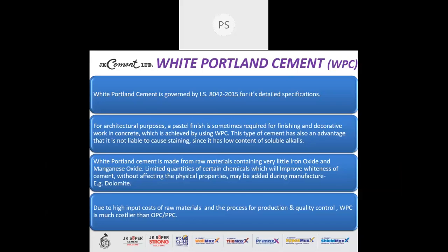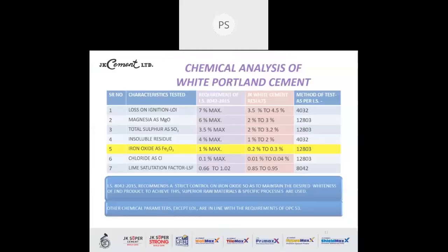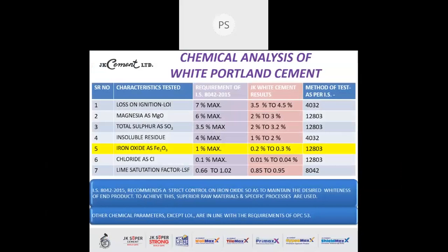Now the chemical analysis first. All the points from point number 7 in the chemical analysis are more or less in line with the OPC except for point number 5, which is the iron oxide. The iron oxide expressed as Fe2O3 should be 1% maximum. Now, as I said earlier, iron oxide and manganese oxide and a few other oxides are the main reason for the grey color of the grey cement. They impart grey color to the grey cement. And that is why the IS code says there should be a permissible limit to it, 1% maximum. JK White cement has a range of 0.2 to 0.3% for the iron oxide content.